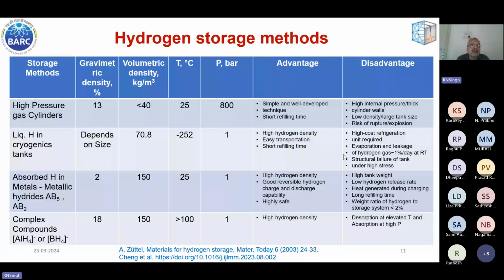Now, for absorbed hydrogen in a metallic lattice, mainly two types of metallic hydrides are there, AB5 and AB2, and the gravimetric density here is very low, only 2%. However, volumetric density as high as 150 kg per cubic meter can be achieved. Temperature is only 25 degrees Celsius. Pressure is also not a concern. High hydrogen density is the advantage. Good reversible hydrogen charging and discharging capability is there. It is highly safe. However, the disadvantages are high tank weight, low hydrogen release rate, heat generated during charging, and a very long refilling time. The weight ratio of hydrogen to storage system is less than 2% presently.